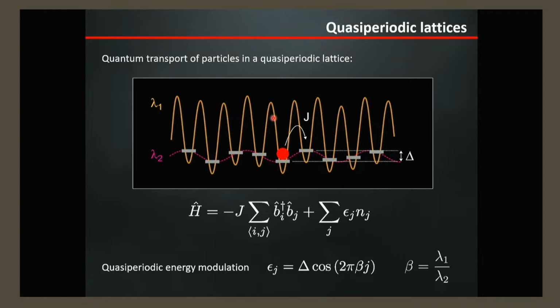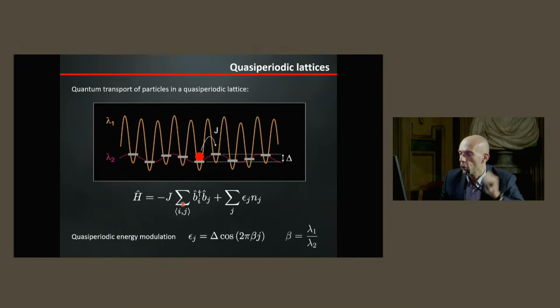So a lattice with some period lambda 1 and modulations of the energy with a non-commensurate wavelength, so you lose periodicity in the system. But still you have long-range order because you can deterministically describe the energies of each site. This beta is an irrational number, meaning that you have no periodicity, no recurrence, no super lattice periods in the system.